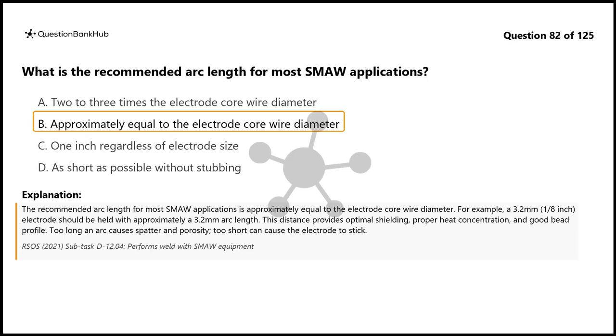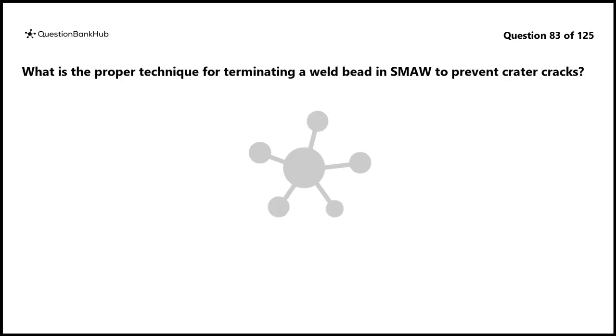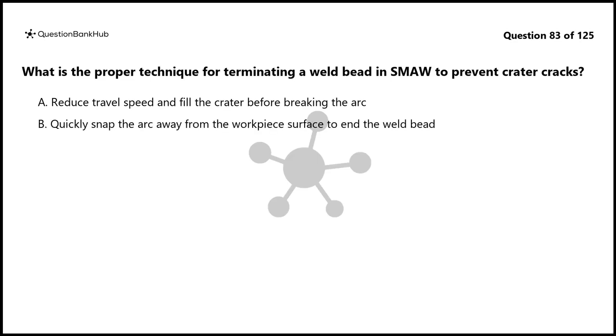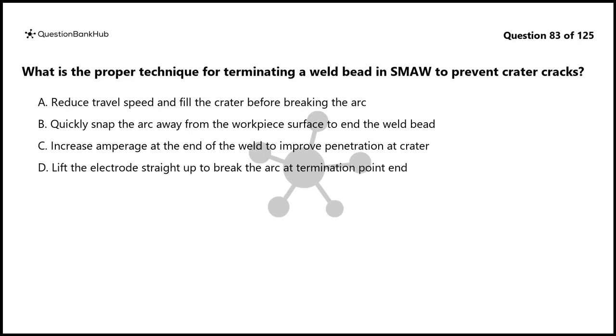Too long an arc causes spatter and porosity, too short can cause the electrode to stick. Question 83. What is the proper technique for terminating a weld bead in SMAW to prevent crater cracks? A. Reduce travel speed and fill the crater before breaking the arc. B. Quickly snap the arc away from the workpiece surface to end the weld bead. C. Increase amperage at the end of the weld to improve penetration at crater. D. Lift the electrode straight up to break the arc at termination point end.